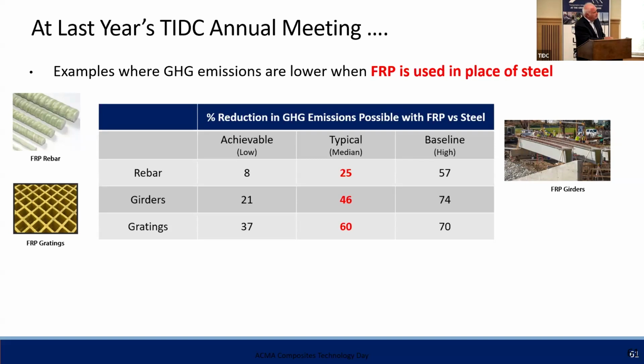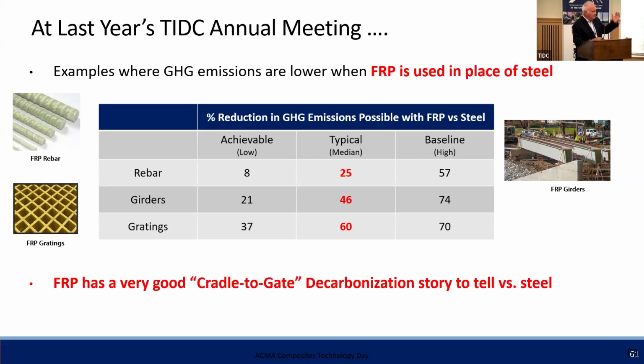I'm just going to focus on the middle column, highlighted in red, because it's the typical values for steel. And what do you see? A 25% reduction for rebar, a 46% reduction for the girders, a 60% reduction for the gratings. All double-digit reductions in emissions when you replace steel by FRP. So if you summarize all this, and this was the take-home message last year, FRP has a very good cradle-to-gate decarbonization story to tell versus steel. And the main reason is that FRP is 70% lighter than steel.